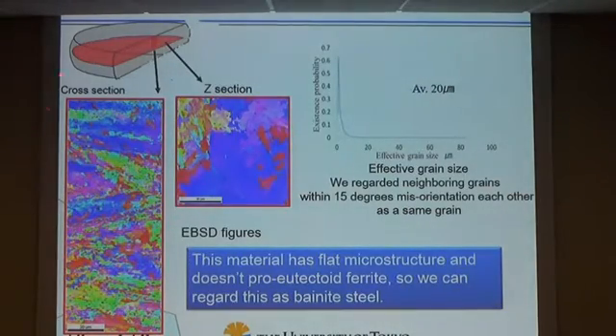And then we took EBSD patterns of the specimens on two sections, cross section and Z section. And then we measured the effective grain size distribution on the cross section. We regarded each adjacent grain as the same grain when their misorientation is within 15 degrees. And this cross-section EBSD pattern shows flat microstructure, and doesn't have proeutectoid ferrite. And each of these grains consisted of small groups of grains which have very near orientation. So we can regard this as bainitic ferrite, bainite steel.